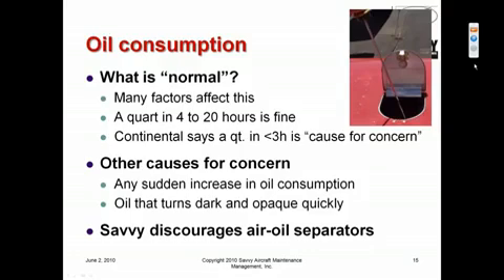there were two other things that concern me other than oil consumption that's, say, more than 1/3 of a quart an hour. One is any sudden increase in oil consumption. If an engine has a history of burning a quart in 10 hours, for example, and all of a sudden it starts burning a quart in 5 hours. A quart in 5 hours is not excessive, but the fact that it suddenly changed from burning a quart in 10 to a quart in 5 means that something changed in the engine.